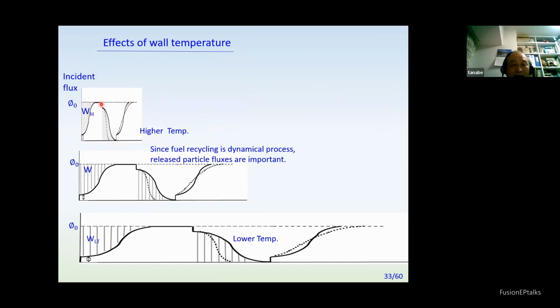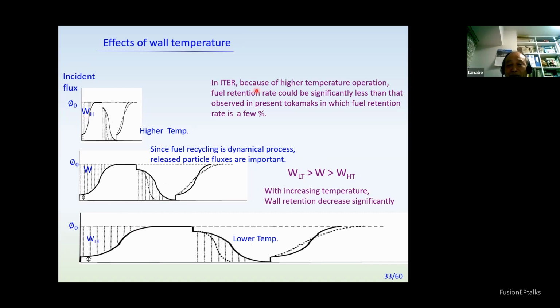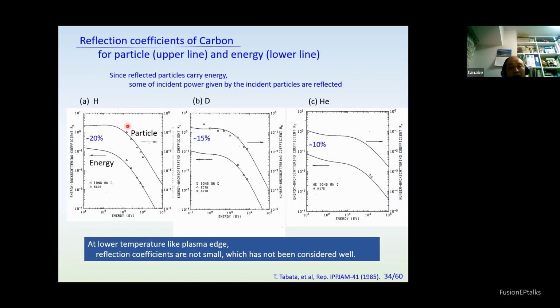Saturation comes very early, and with increasing temperature, total retention becomes less. Because of high temperature operation, the fuel retention rate could be significantly less than the present observed value, which is a few percent. So high temperature operation is rather promising.